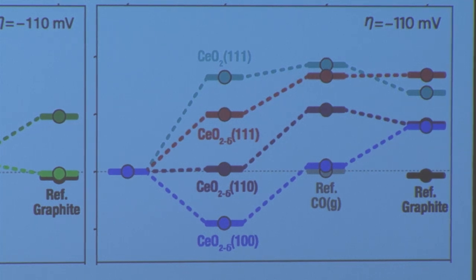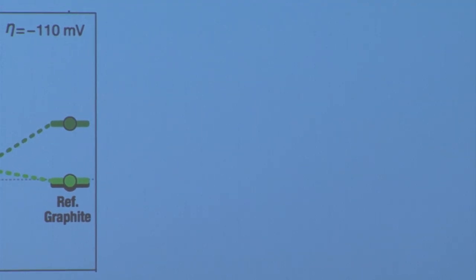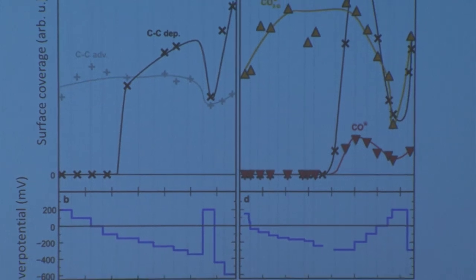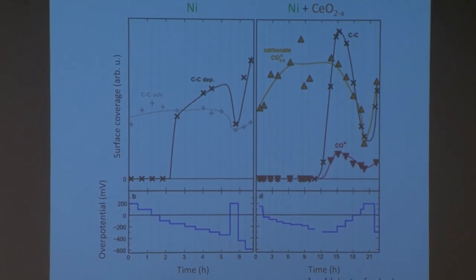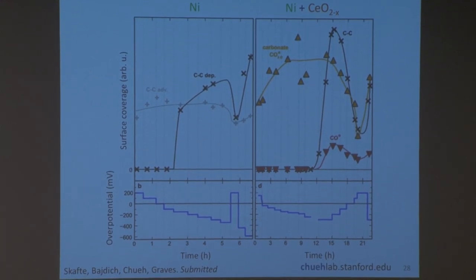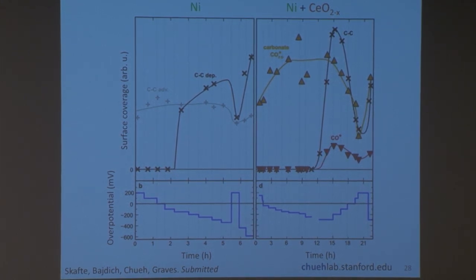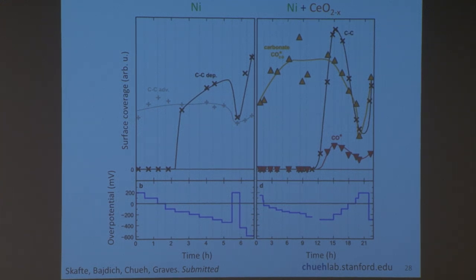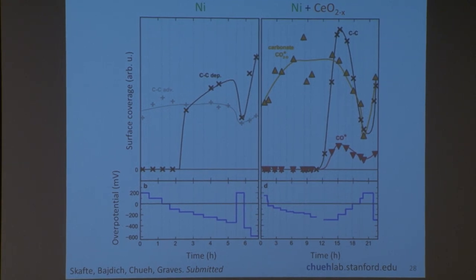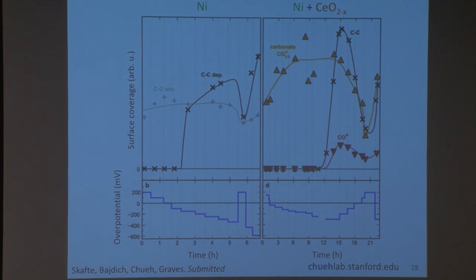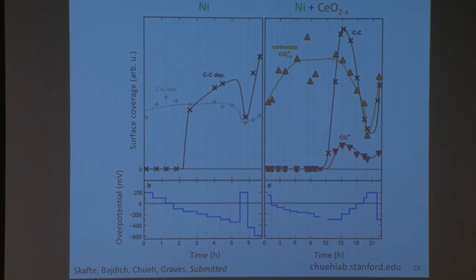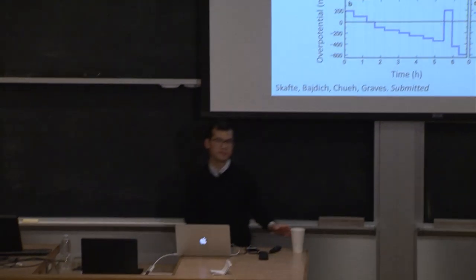transiently. And I didn't show this. It's actually really neat data in the transient data. So you can see here, as the carbon peak comes up, you actually see a small presence of the carboxylate, which is weird, but that's telling you actually the carbonate is reacting with the carbon to make the carboxylate. So this is called the reverse Boudouard reaction. So you're actually consuming the carbon in the process of doing this. Thank you. Got a question over here.